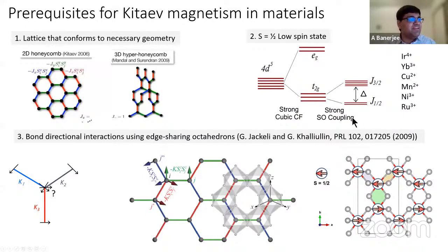Thirdly, if you have a strong cubic crystal field, let's say that this is the cation and these are the anions. If you have the cation surrounded by an octahedral cage of anions, what you find is that this cation anion forms a square. Well, this is a 3D model, so this doesn't look like a square, but this is really a 3D square which faces 3 different directions. And as it turns out, because of the Goodenough-Kanamori rules, all the Heisenberg interactions cancel out. The only interaction which survives is the Ising interaction which comes out of that square. So if you have the plane of the square, the only interaction which survives is the interaction which comes out of the plane of that square.